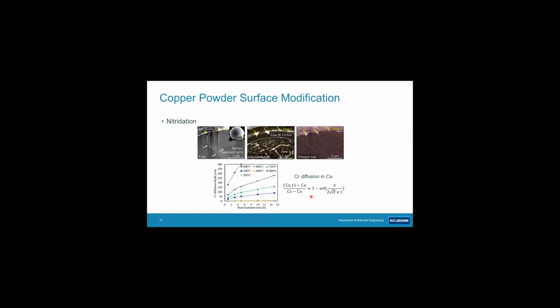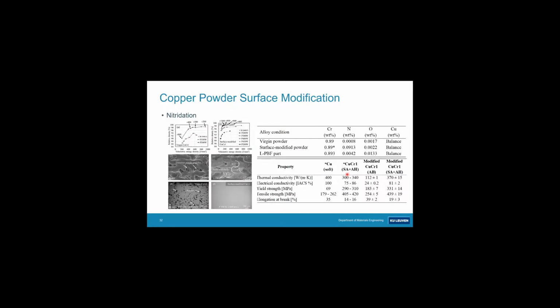Again, this enhances absorption a lot, and the thickness of the layer could be controlled because it really matches very well with, you can control the chromium diffusion behavior simply by calculating it with Fick's second law of diffusion. So we have a control over the thickness of the layer.